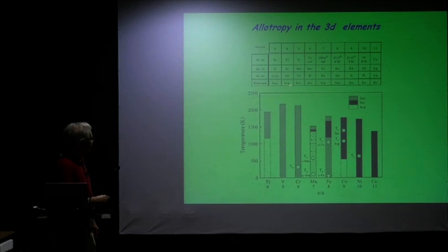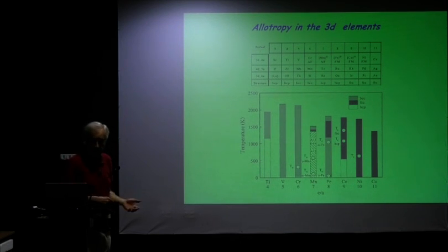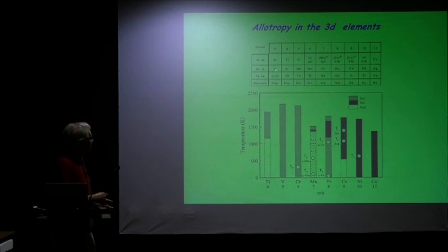Titanium is hexagonal at low temperature, but it becomes body-centered cubic at high temperature. Scandium, it's not shown here, but it's all hexagonal. And then when you go to vanadium and chromium, you find the body-centered cubic stabilizing all throughout the temperature range. Vanadium is paramagnetic, and chromium has a Néel temperature around 312 Kelvin. So you see that this BCC region opens up.